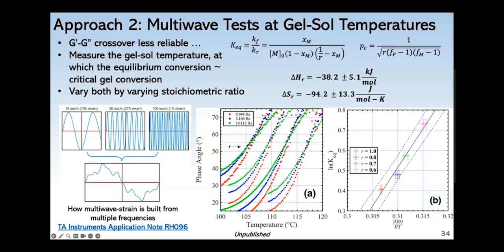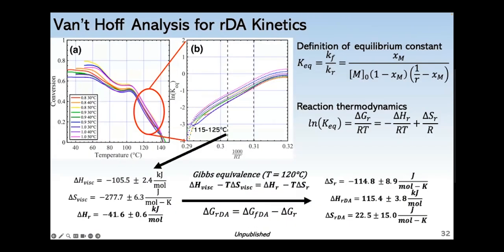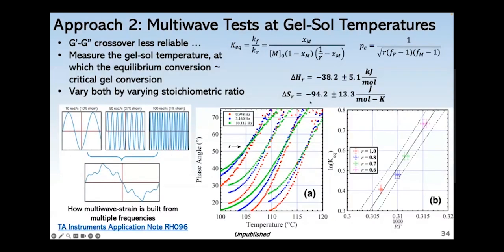So I then calculated the equilibrium constant using Flory-Stockmayer conversion and plotted that against the degelation temperature, like I've shown in plot B. And once I fit again a van 't Hoff curve to this, I have the reaction thermodynamic parameters, which are in pretty good agreement with the values shown on the previous slide. So minus 40 roughly, and minus 100 for the enthalpy and entropy.